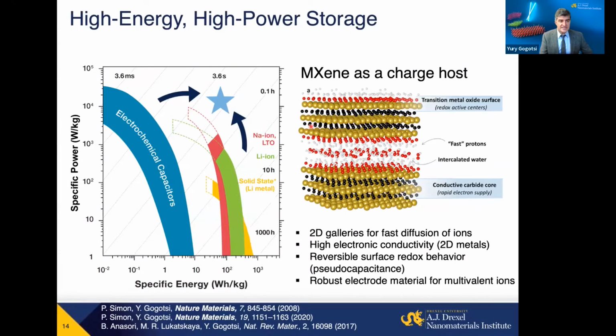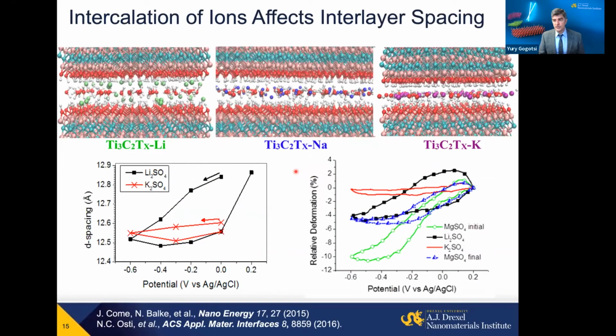And actually, MXenes answer all those demands. They are metallically conducting, as I mentioned. They are 2-3 orders of magnitude more conducting compared to activated carbons, at least titanium carbide MXene, that are used in double layer capacitors, which are considered to be the fastest, highest power energy storage devices. They have galleries between the layers where ions can move. They also have transition metal on the surface, which can change oxidation state. And this is something that may be invaluable in designing future energy storage systems.